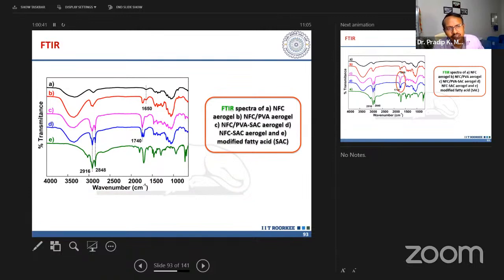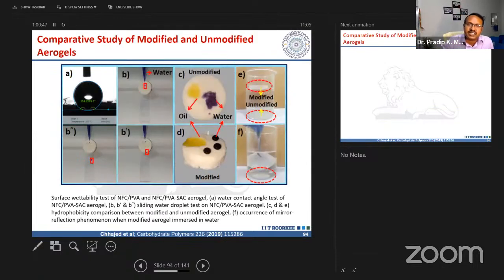From the chemistry point of view, we have tried to check what the chemistry behind it is. I'm not going into details, but related to the technology, I'm trying to tell you how we have achieved almost a 160-degree contact angle. Try to realize a 160-degree contact angle; it is really super hydrophobic. Above 120, it is super hydrophobic. When it is unmodified cellulose, it takes water and oil together, while the modified cellulose aerogel does not take water at all. We have added some pigment so that we can distinguish it. You see, the water is rounded like anything. So this material can be utilized for oil-water separation.